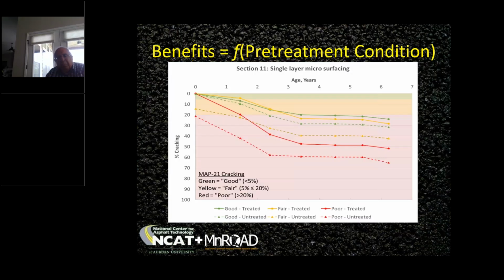For example, this is a benefit curve for a single layer microsurface. What you see in these curves is that the solid lines are cracking that we map after treatment, and the dashed lines are where cracking would be, based on control sections, if we had not applied the treatments. So for single layer microsurface, what I've shaded in yellow is the benefit of microsurface when the pavement is in a fair condition before the microsurface is applied. And you can do the same thing for good and for poor.